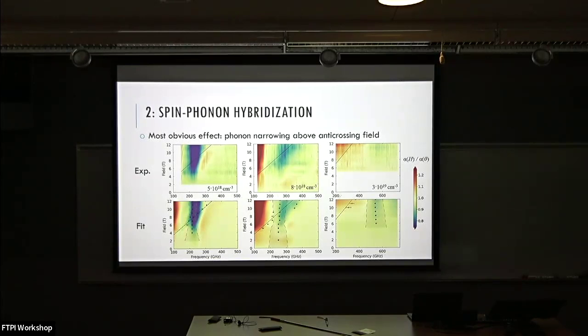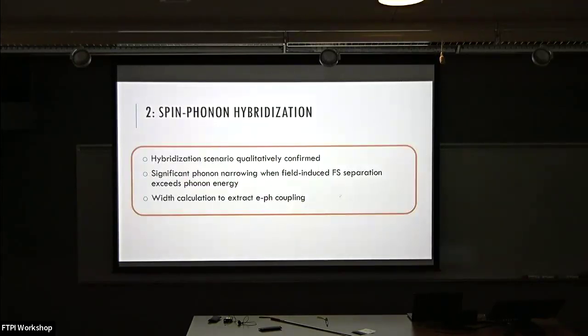Now, in the theory paper I mentioned before, this is not in there. They just assume that the phonon is perfectly sharp, which is of course not the case. But here, we definitely see this. And the hope is that we can actually use this narrowing to extract the coupling.